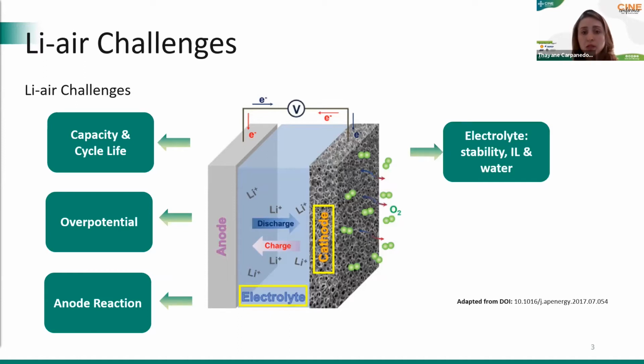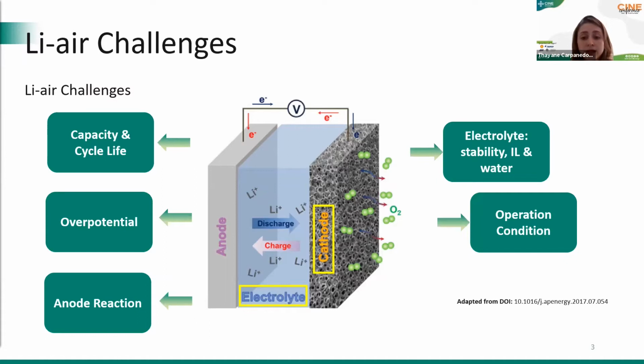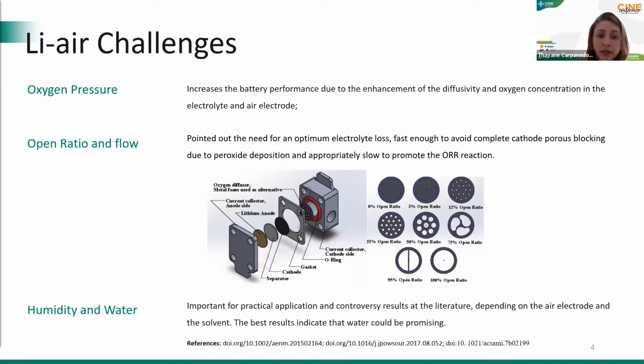And the electrolyte is one of our lines. We study the stability and also the addition of ionic liquid, as Cheyenne explained before, and also water to improve the battery's performance. And besides, we studied the operation condition related with the oxygen supply, because it's a really important parameter to be understood and optimized, focusing mainly on practical application. And it's reported in the literature regarding the operation condition that the oxygen pressure increased the battery performance due to the enhancement of the diffusivity and oxygen concentration in the electrolyte and air electrode.